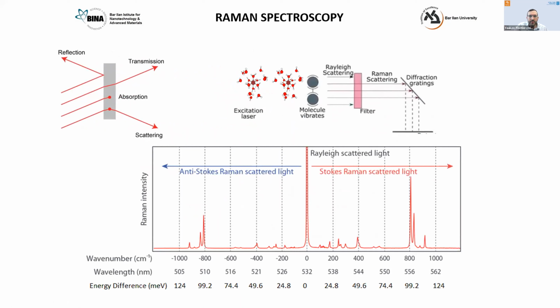And a typical Raman spectrum may look something like this. So in this case, the excitation wavelength is 532 nanometers, and we'll see peaks that are red shifted, otherwise known as the Stokes Raman scattered, as well as peaks that are blue shifted, the anti-Stokes peaks. And typically in the spectroscopy community, one looks at this in terms of wave numbers because wave numbers scales linearly with energy.